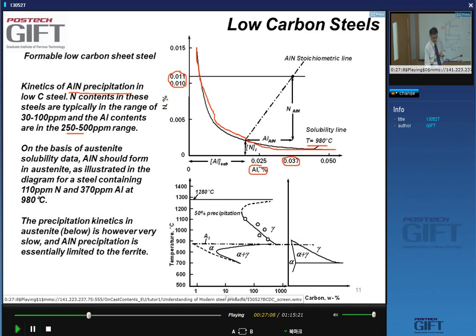So remember what this means. All the compositions that are below here, the aluminum nitride will be in solution. Compositions above this line will give me aluminum nitride precipitation in thermodynamic equilibrium. So if I have 110 ppm of nitrogen and 370 ppm of aluminum, I have this point here, and that means that I will have precipitation of aluminum nitride. So on the basis of austenite solubility data, aluminum nitride should precipitate in the austenite.